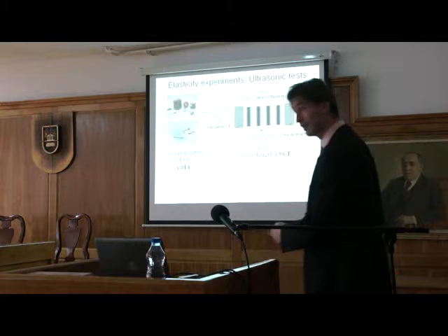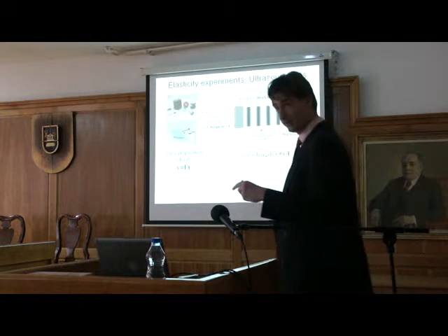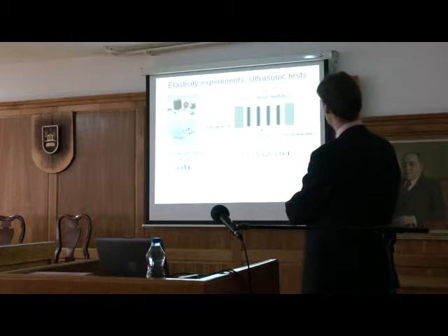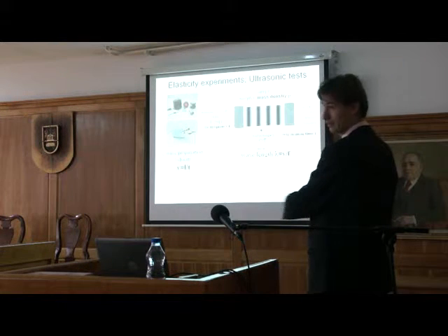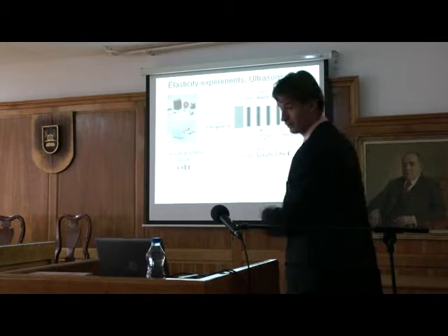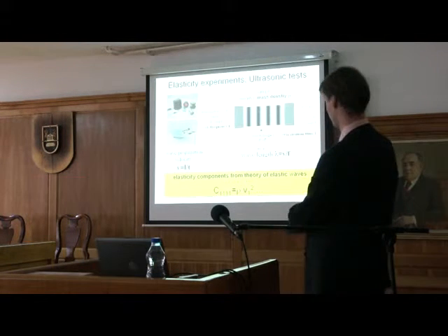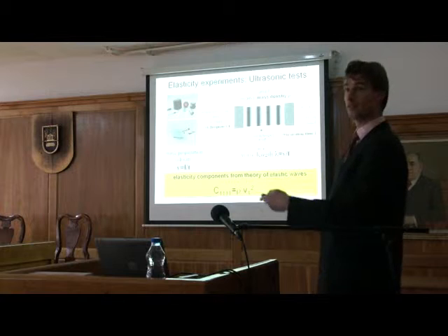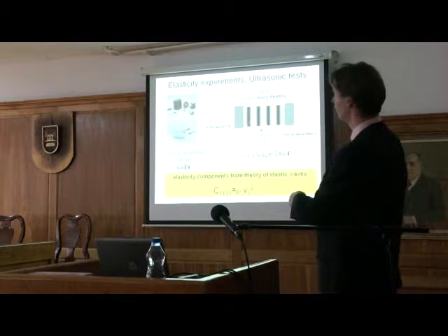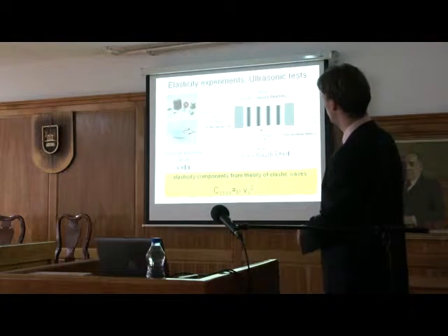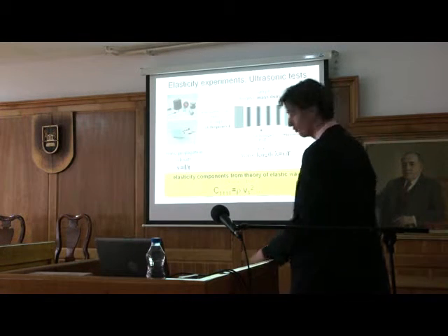But still, if you change the wavelength, then you can characterize the material at different scales non-destructively, as long as the waves go more or less straight through the material. Once you have big deviations, then it's not correct anymore. But this we use extensively, so we have different frequencies, and the different frequencies we send to the materials in different directions, and then we get more or less the full elasticity tensor with the correct mass densities and so on.